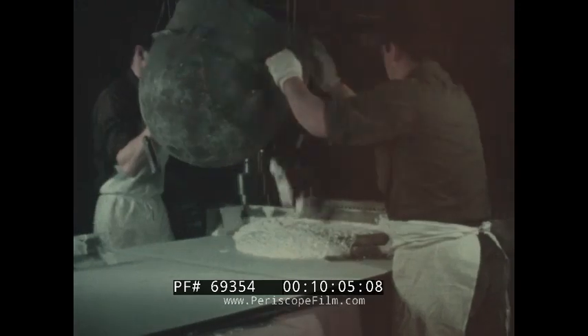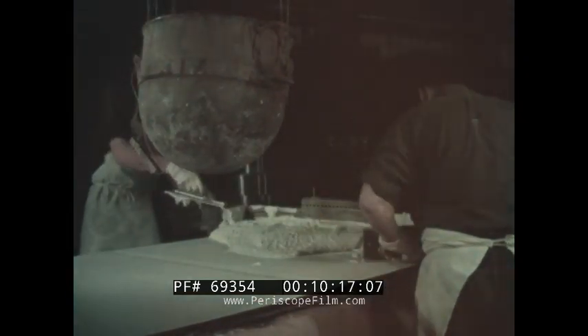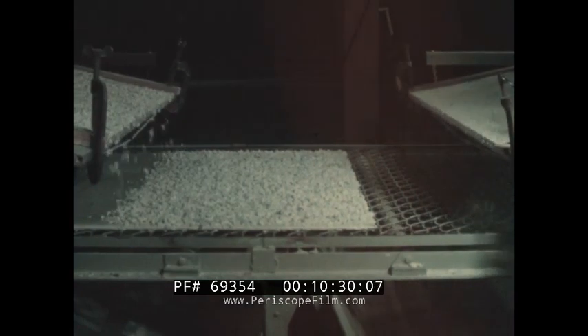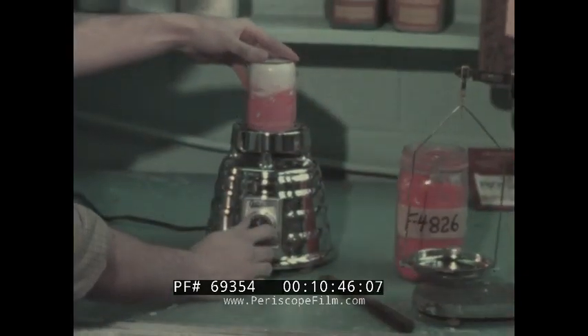The Mirror Rock aggregate paneling system is produced essentially the same way, with cement asbestos board as its base. For balanced panel construction and to ensure flatness, a sheet of Mirror Clad porcelain enamel on steel is laminated to the back of this board, and to the face a special color-keyed epoxy resin is applied uniformly. Permacore and other materials can be used to increase insulation. The aggregate is then evenly distributed across the panel and passes under suspension rollers which set it into the epoxy resin. After a short curing time, the finished panels are ready for delivery.